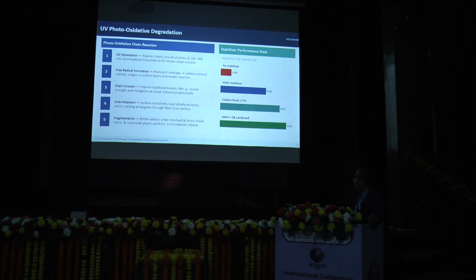And if we add amine-type stabilizers, it can reduce the microplastic generation. Another method of reducing the UV effect is carbon black. If we treat the fibers with carbon black, a coating is made onto the fibers and the exposure to the UV light can be reduced. And if you give both carbon black along with the HALS, the efficiency of the product would be much increased.